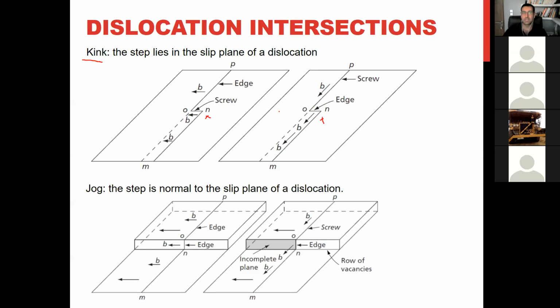Kink means this step that is formed lies in the slip plane of the dislocation. It means this is the plane and this step on the dislocation is inside of the slip plane. It can be edge or screw, depending on the direction of the Burgers vector. Elimination of this kind of kink is very easy. If this dislocation moves, this step will be eliminated.